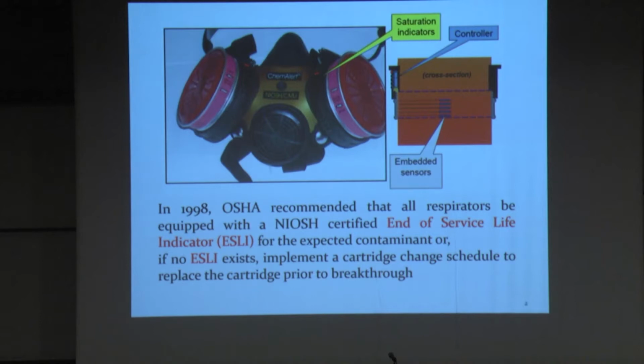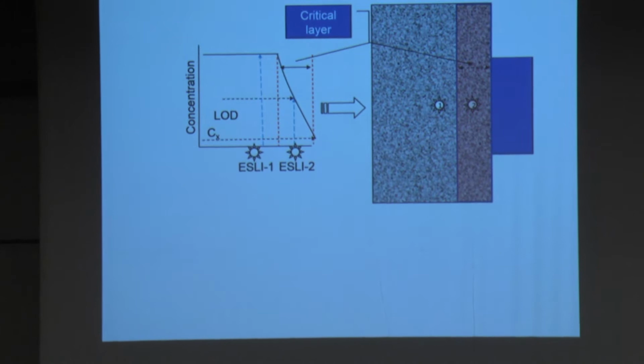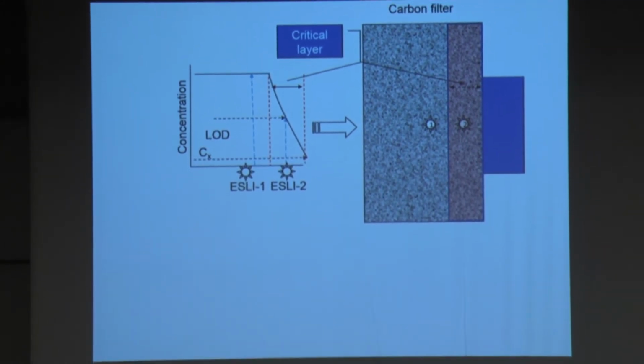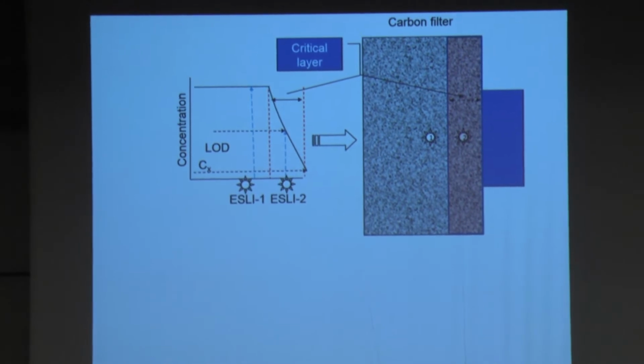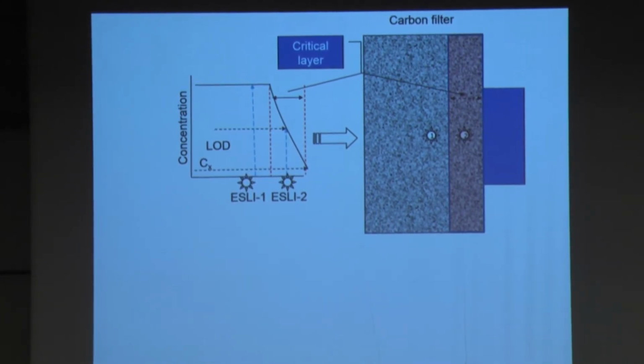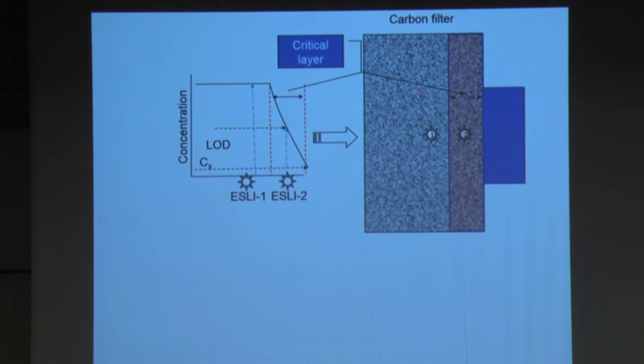Some words about the chemistry and physics of carbon cartridges. When an analyte is absorbed, the carbon saturates, and then the saturation front travels along the cartridge until it reaches a point called the critical layer, where there is an exponential decay in concentration. However, there's a finite concentration of analyte coming out of the carbon cartridge. At this point, the cartridge is no good anymore. The trick is to find out when this happens before any analyte leaks into the mask.